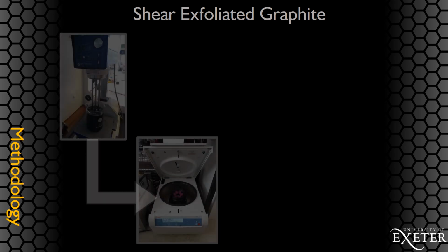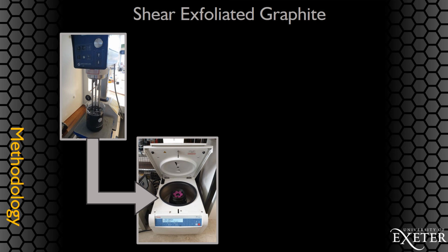Shear exfoliated graphite follows a different process. Graphite flakes, water and sodium cholate are first shear mixed at high speed before centrifuging further. This isolates the graphene in suspension and is eventually separated out from the remaining waste graphite chunks.